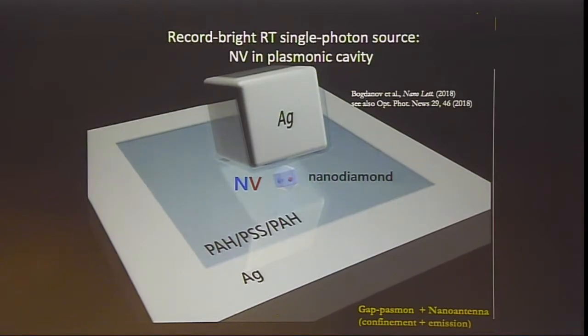By large, I mean like 100 nanometers, whereas the gap itself is on the scale of 10 nanometers. Because of this strong confinement, you have a very strong enhancement in nonlinear, in light-matter coupling. But you need to outcouple these single photons, coming for example from a nitrogen vacancy in nanodiamond, very fast, before decoherence happens. For that, you need a really efficient, relatively large antenna. So there is a strong increase in light-matter coupling because of these gap plasmons, and very fast outcoupling because of this nanopatch antenna.